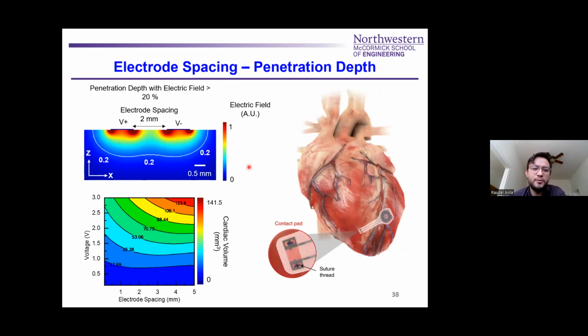And then we can also study its penetration depths, and this is more on the last part of the electrode, where you can study electrode spacing and understand how the electric field is going to decay in the tissue as a function of distance away from the electrode, depending on the amount of voltage that you supply, and the spacing. You can calculate the volume of cardiac tissue that is within a certain threshold. So in this case, this 0.2 here is pointing to the electric field having decayed about 80% at this specific distance from your electrode surface.